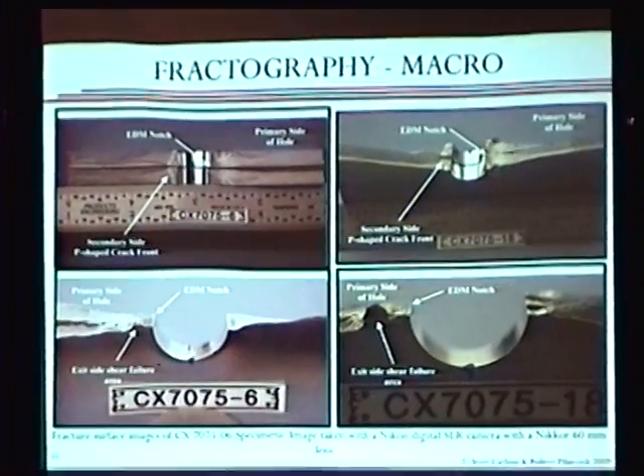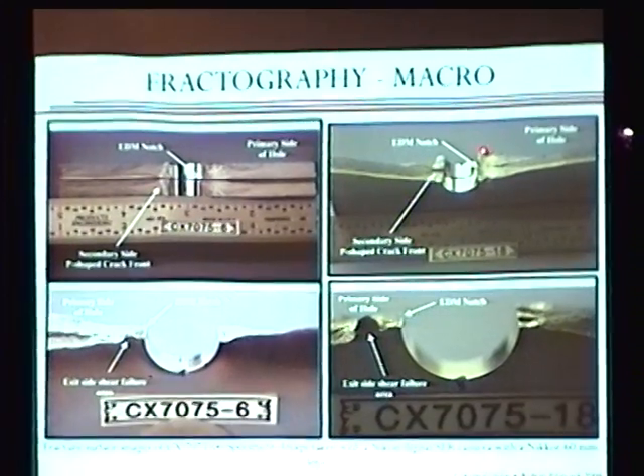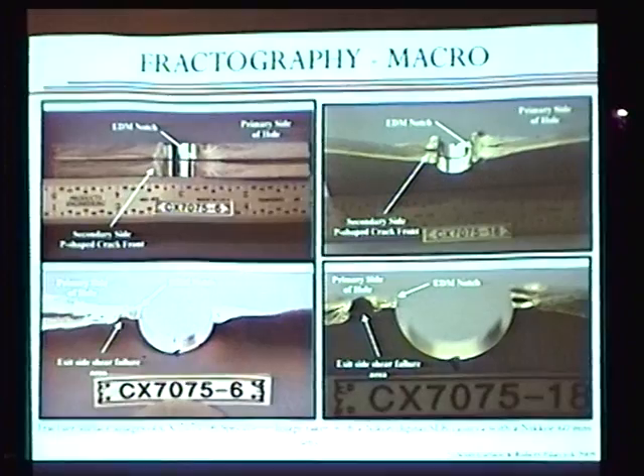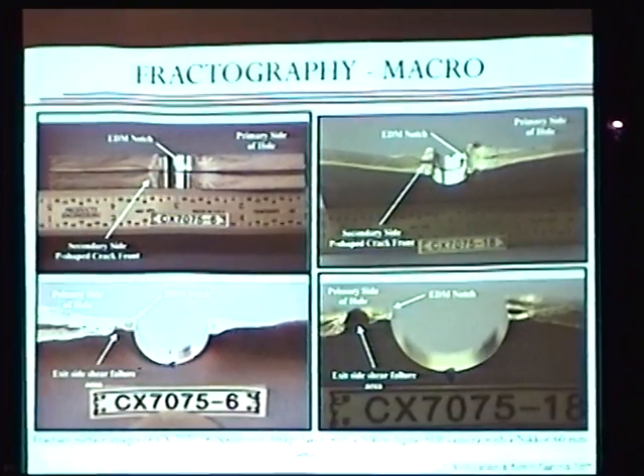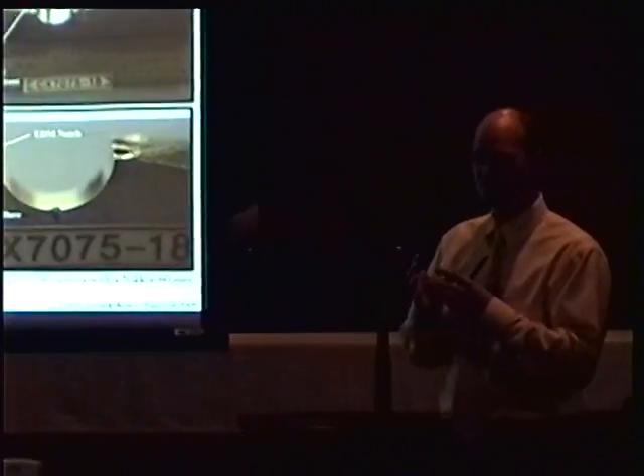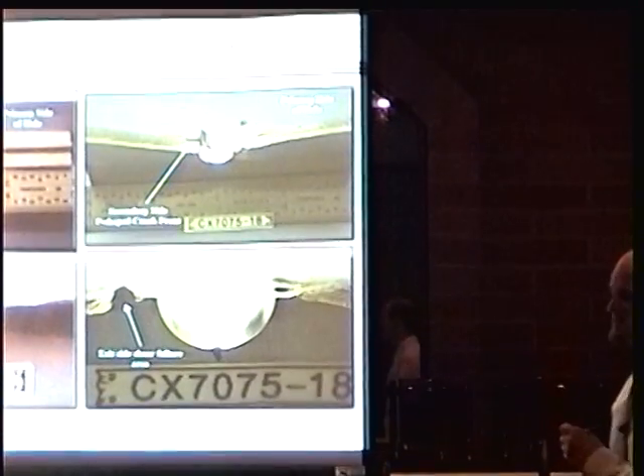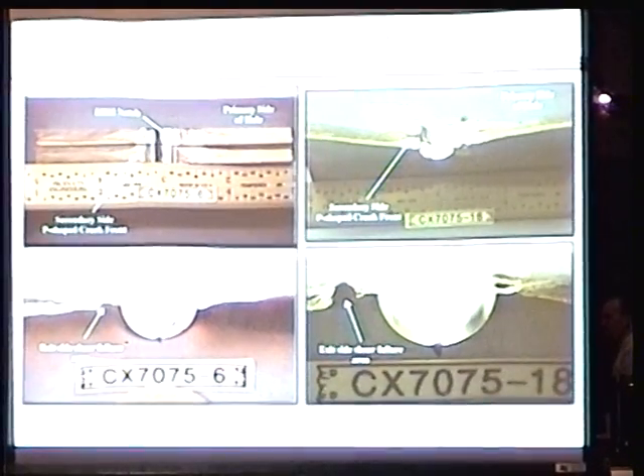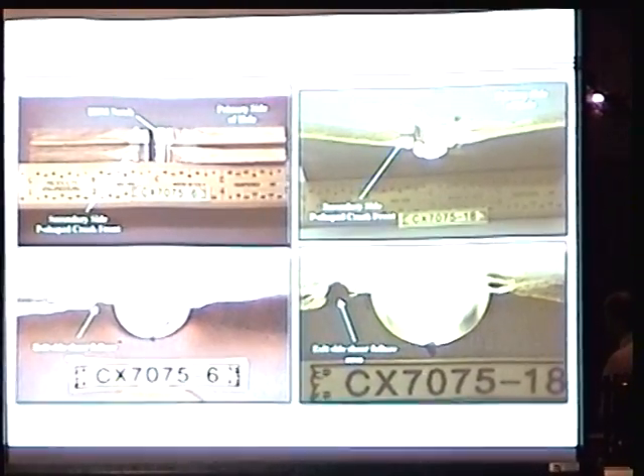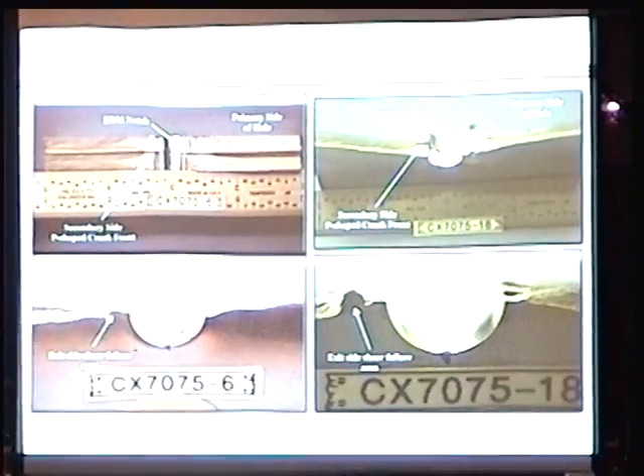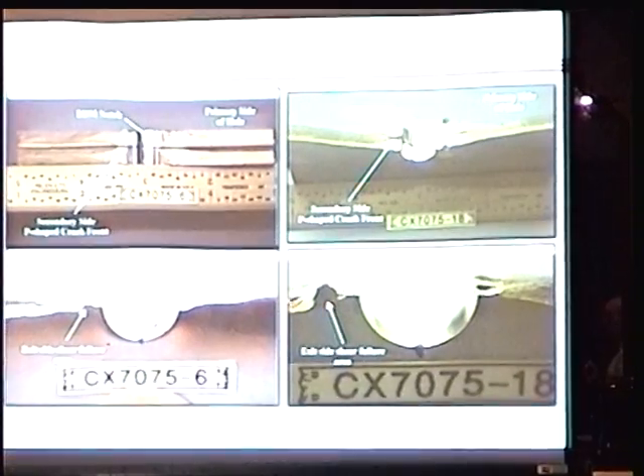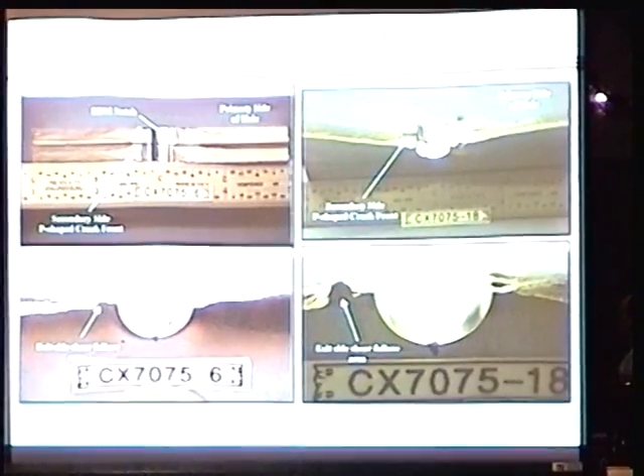The other thing I wanted to talk about, and I've got some really cool pictures coming up, is this really unique tearing area, and this is an artifact of that really high residual stress I was talking about. You have this area on the exit side of the specimen where the residual stress is so high that the crack just doesn't want to propagate through that area. What we saw in our testing is these cracks would start to grow right here in the EDM notch, and they'd hit this little area over here, and they'd say, I'm not going to propagate through there, I'm going to go all the way around. So we would have cracks growing around this whole area. You'd have a little crack show right here, nothing right here, a little crack pop through clear over here, and then all of a sudden this would just fracture. It would completely grow around that high residual stress area, and finally it got to the point where it couldn't take it anymore. But that could be a problem, because just below the surface you might have a crack clear out here that you can't see on the surface. So it's something to keep in mind.